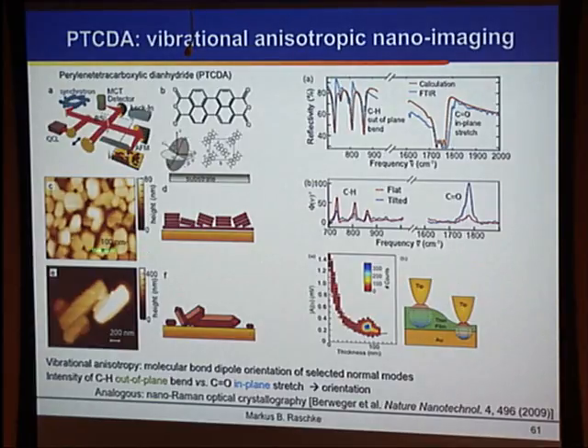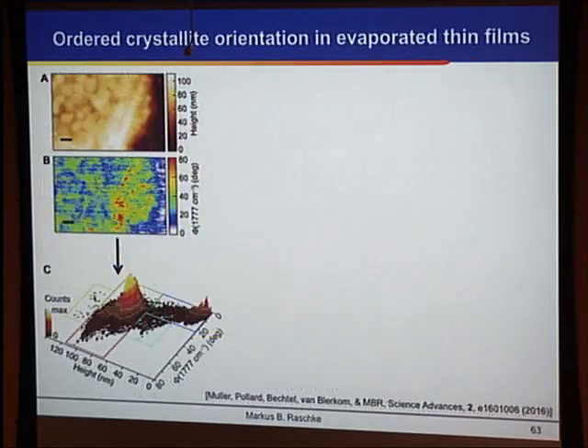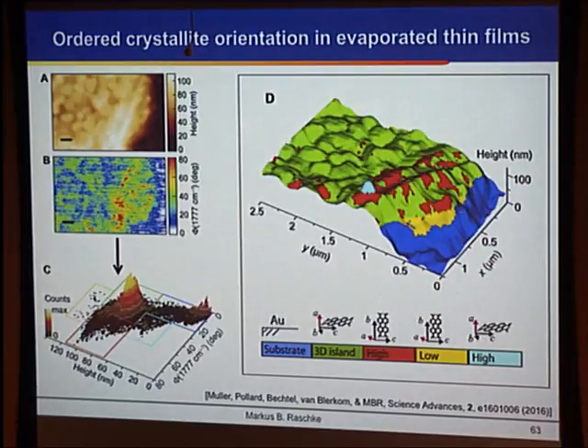And this allows us then, in heterogeneous films or single crystal structures, to really determine the molecular orientation and really do optical infrared crystallography on the nanoscale with this type of spectroscopy, looking at multi-vibrational modes simultaneously. And so here, by combining the spectroscopic data, including different scanning probe signals on these different references, and mapping and binning these in appropriate distributions, we can really get a spatial distribution map of the molecules here, a disordered electrode interface, where we see 3D islands where the molecules are flat, and then at the edges we see a lot of disorder, where then we get molecular aggregates of different order. And this is why, if you have charge transport, which is predominantly in plane, suddenly we get inhibition of the carrier transport as we go into the electrode interface.